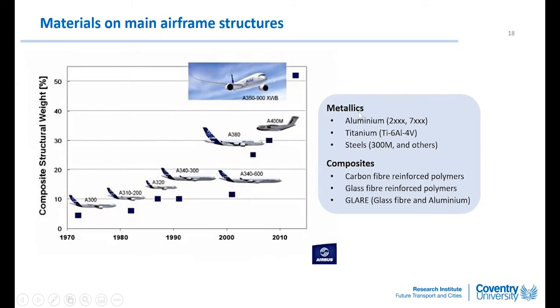The metallic materials on this aircraft are dominated by aluminum alloys. 2000 series are very good for fatigue resistance, so they are used for making wings and fuselage shells. 7000 series are used for spars, stringers, and ribs because they are high strength and high stiffness. We also have titanium alloys used for fittings and joints. Titanium alloy use will increase as we introduce composites because aluminum has a galvanic corrosion problem with carbon fiber. So titanium usage will increase.